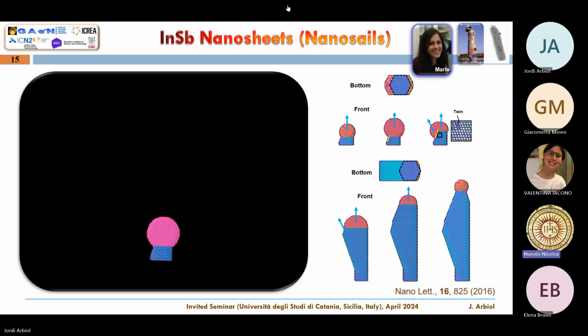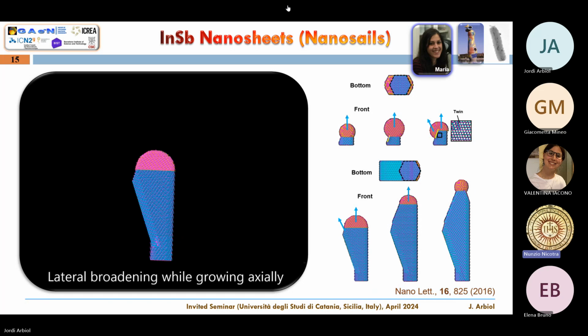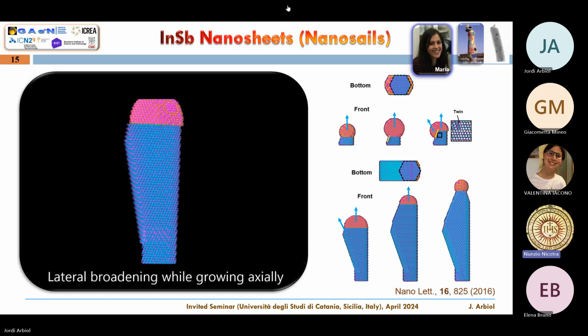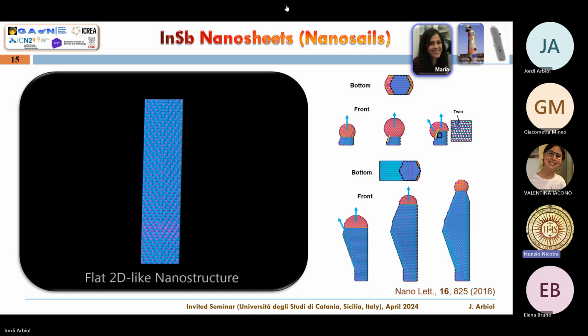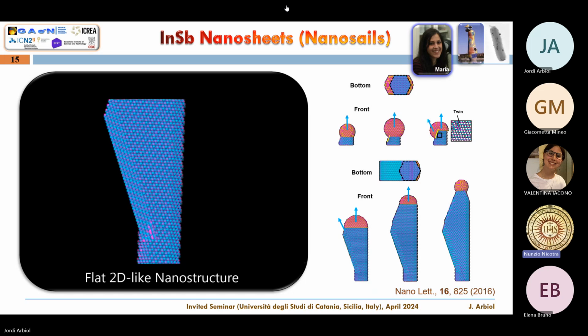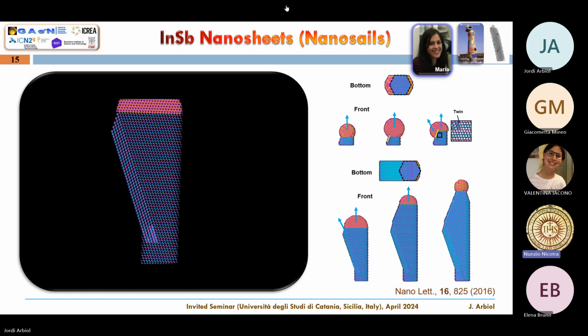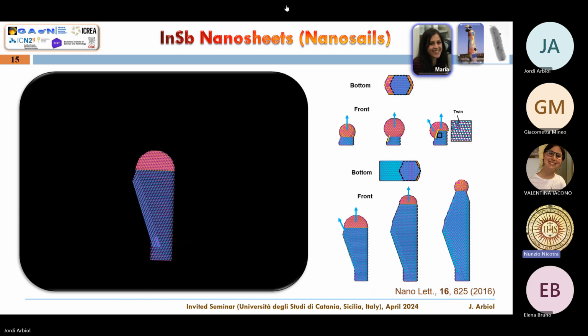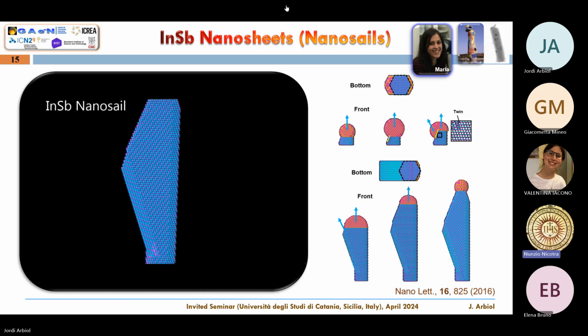And when it grows, from time to time, this droplet tends to fall to one of the sides. And when it falls, it creates this twin boundary that breaks the symmetry and allows the material to grow to this other surface, which is not unpolar anymore, because it has this axial polarity with the cation, with the anion on top. So you can grow to the side and continue growing until you get rid of the small indium gold droplet, which gets smaller, smaller, and smaller. Okay, so this is the growth mechanism of this nanosail.